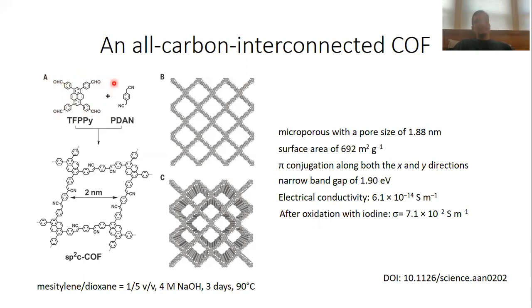with a nitrile that has a CH2 group in between the nitrile unit and the phenyl unit here. So this nitrile unit is a quite electron withdrawing unit, and for that reason the carbon-hydrogen bonds of the CH2 groups here are somewhat acidic.